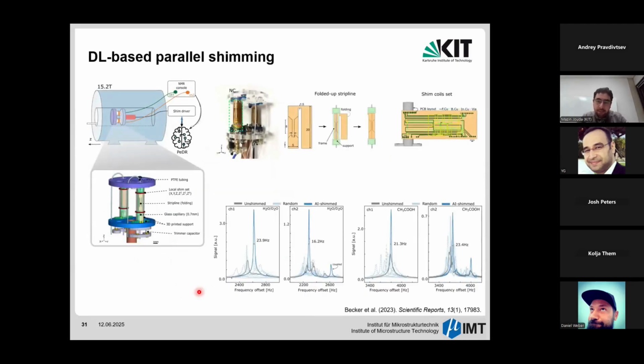After that, we applied this method to parallel spectroscopy, at the high field system. So this is a home-built probe that has 2 NMR detectors, and each detector is equipped with a set of shimming coils comprising 6 shim coils, namely X, Y, Z plus Z square, Z cube and Z to the power 4. Again, we need to collect a large data set for training from the parallel setup, and then we modified the AI model to be trained to predict 12 shim currents simultaneously.